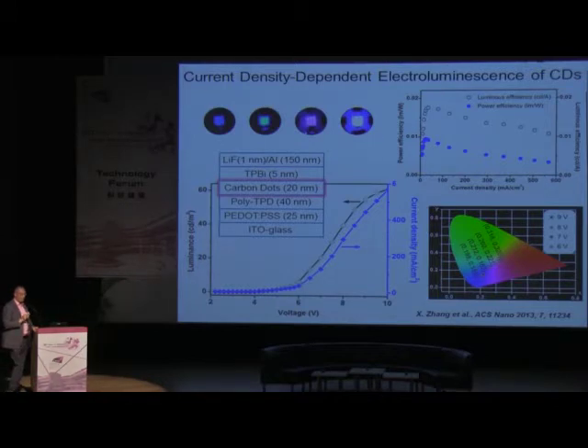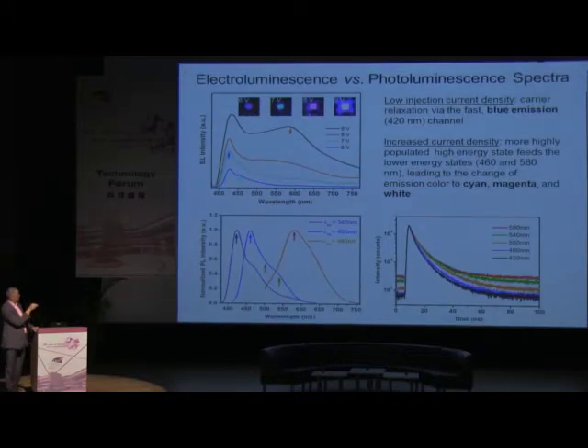current density, on the amount of current we can inject into these devices, which is probably even better seen from here. So if we apply lower voltage, like 6 volt, those devices emit mostly blue light, and if we increase voltage, it moves to cyan, magenta, and white. White is like that.